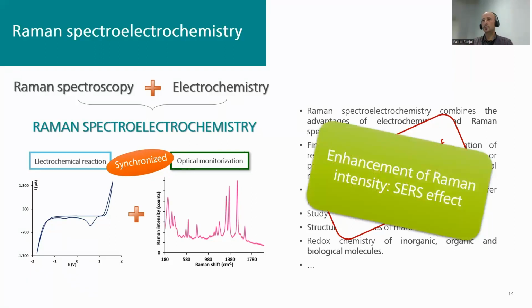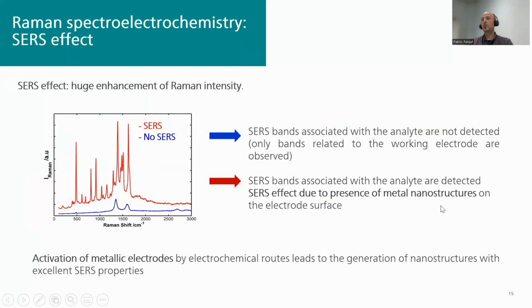So if we would like to increase the sensitivity, we need to work with this SERS effect, surface enhanced Raman spectroscopy effect. And in this case, due to the interaction of the molecules with some specific metallic surfaces, usually gold, copper, or silver, we can enhance a lot the Raman spectra. So we are able to get information about our sample, but we always need, for going to low detection limits, to have this interaction between the analyte molecule with a metallic surface. And as we talk of metallic surfaces, and we are mentioning gold, copper, and silver, then it's when the integration between electrochemistry and SERS is clearly identified, because we can have metallic electrodes, like a gold electrode or a silver electrode, being used as a SERS substrate for SERS Raman spectro-electrochemistry.